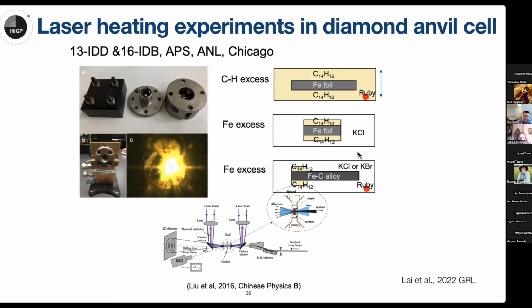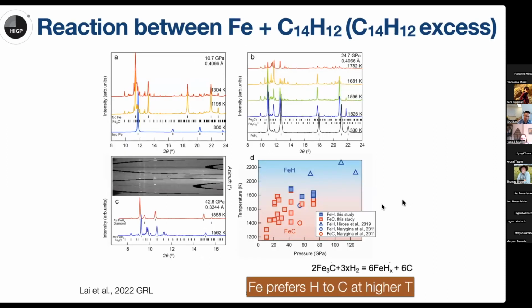This is the experimental setup that we use. We loaded our sample in the symmetric diamond anvil cell, and our sample is iron with the carbon hydrogen source around it. Our sample was also iron carbon alloys reacting with those iron hydrogen sources. The experiment was performed at sector 13 ID-D of the APS. This is a summary of our result. We found that by reacting iron with this carbon hydrogen source, we found the formation of diamond. When we heat it up to 1885 Kelvin, we found the formation of this powder diamond from the reaction.